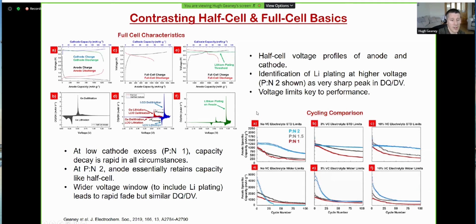So what's very important is the electrolyte composition here. If we look at it as a function of the PN ratio, which is essentially how much cathode excess we had, the blue trends here have more cathode excess, and as we go down to the red, they have less. The best in terms of performance was the one that had VC in the electrolyte, within what we call the standard voltage limits.